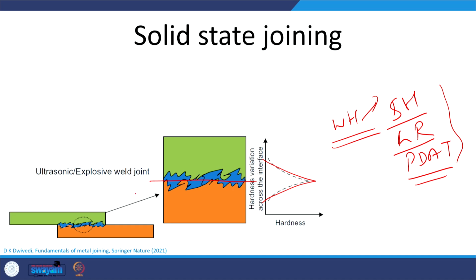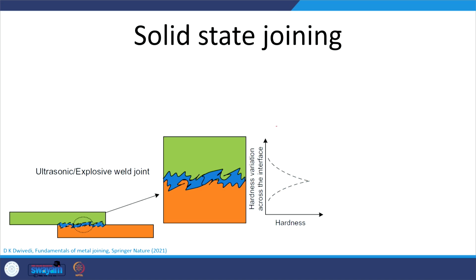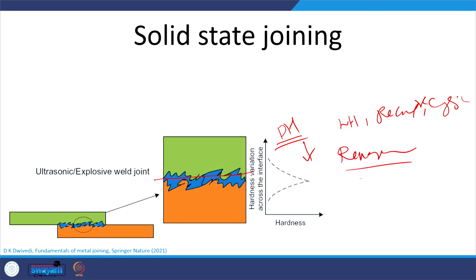Okay. So, at the same time, if the metal is primarily the precipitation hardening kind, then the work hardening, the recovery and recrystallization, the effect of all these things will be very limited. There is no scope for formation of fresh precipitates; rather, due to the heat generation it is possible that some reversion can take place, and that can significantly reduce the kind of interfacial hardness distribution that will be observed.